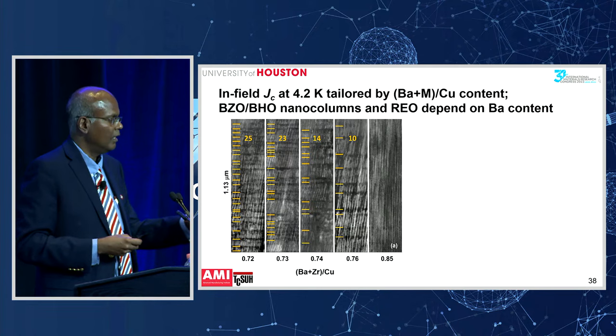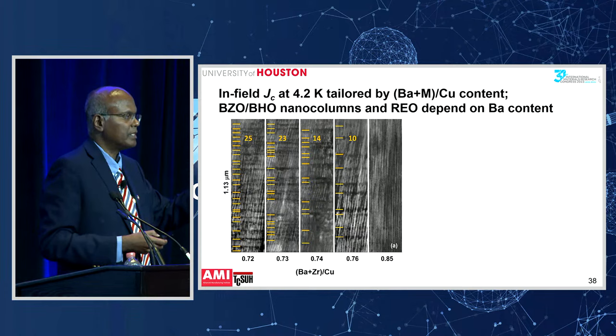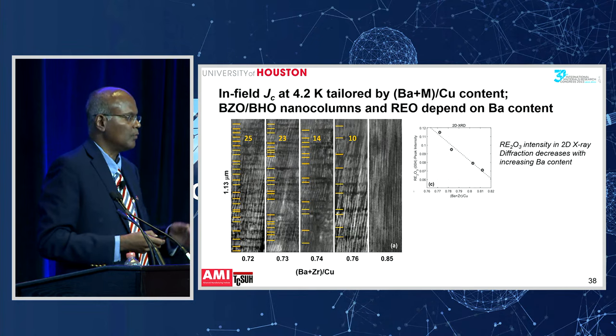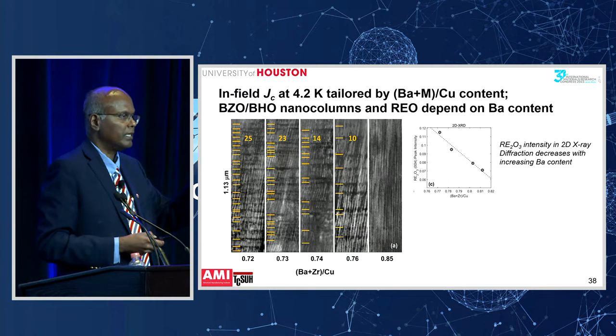So as you increase the barium, you can see one thing is that the rare earth oxide precipitate density decreases, and the barium zirconate columns become a lot more continuous, right? So you can see from this chart that as you increase the barium content, the rare earth oxide intensity actually goes down, in the X-ray diffraction.